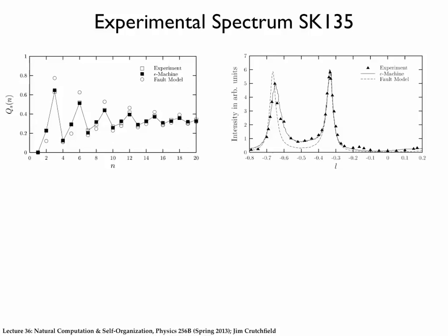2H has the peaks at L equal 0 and L equal a half, or minus a half since it's periodic. So I don't really see a lot of action here. So I'm not thinking 2H is important here. 4H would be something at a quarter, which would be here, and a half, which I'm not seeing much of here, and minus 0.75, let's say, here. So I'm not thinking 4H is important here either. Intuitively, just looking at it, this is all sort of back of the hand.